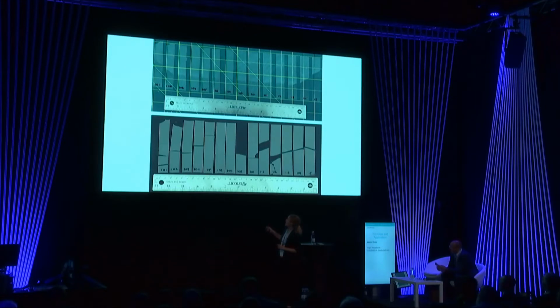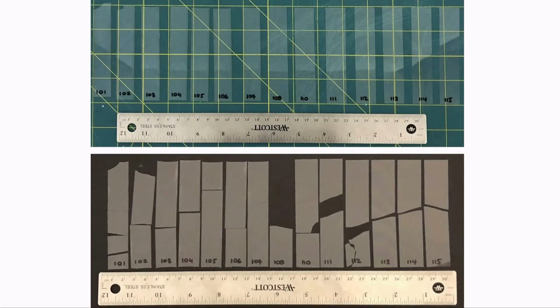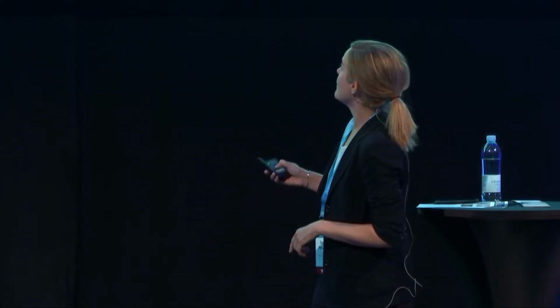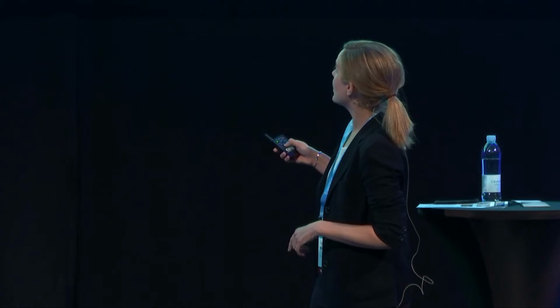You can see how before testing, the short edge condition was not very good. However, the specimens didn't break at those locations, so it was satisfactory breakage, and we used those for the study. We also realized that they were not doing very well, so we decided to manually sand 3 of them. So 1, 2, 3, 4.